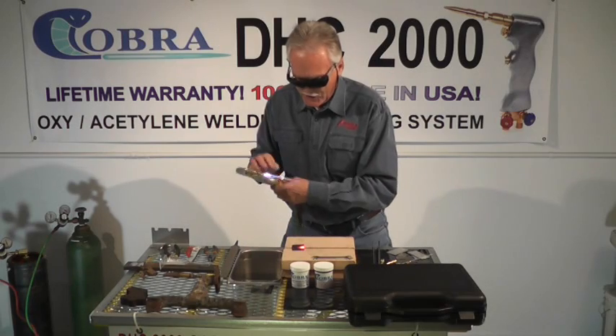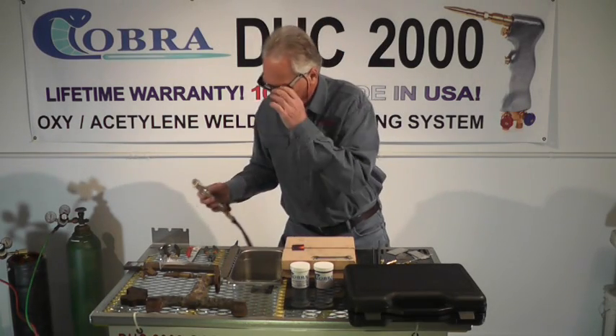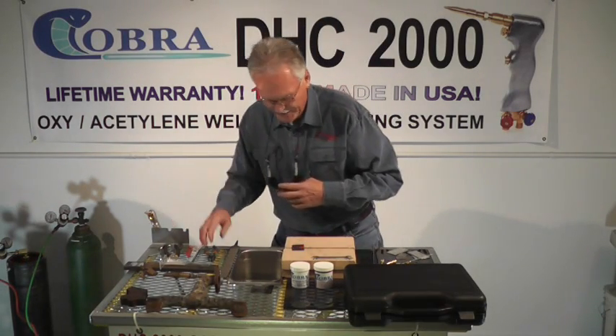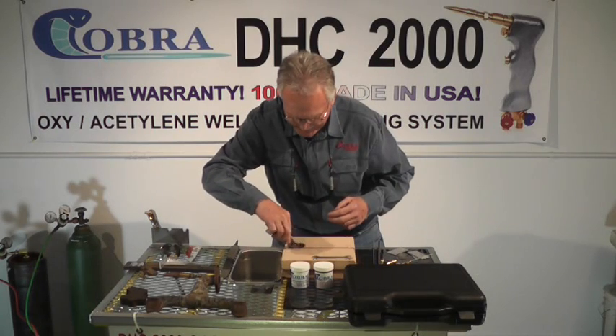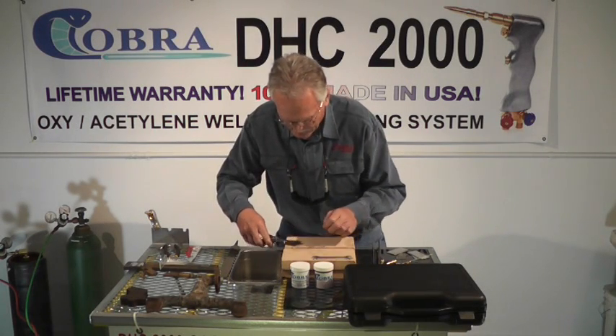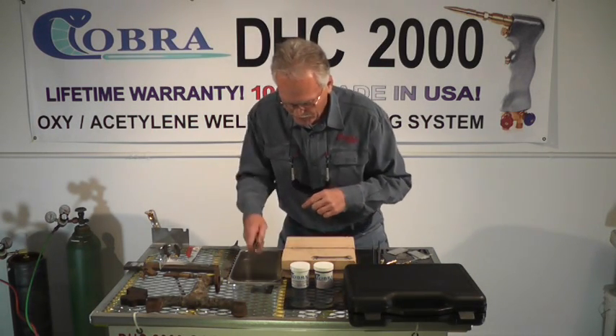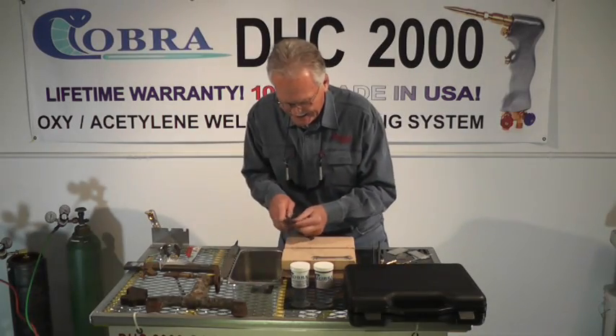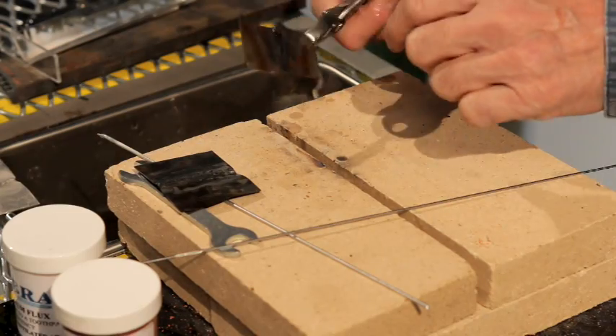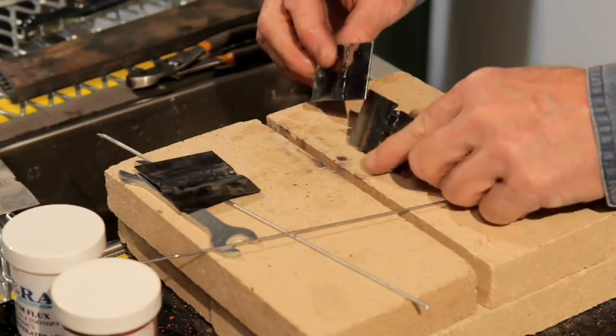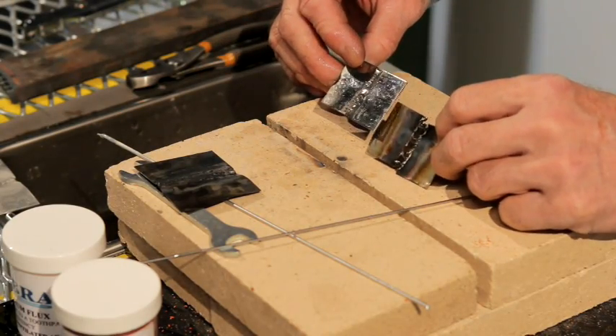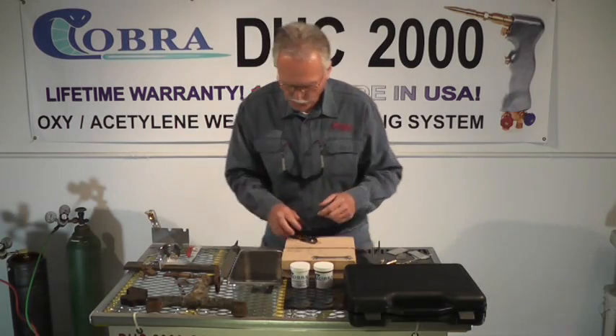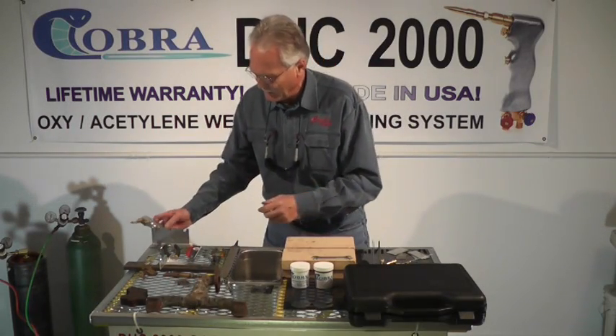Now you're going to get a dark looking weld when you weld with it because of the excess acetylene. You can see your weld, your 100% penetration on it, the stainless. Now see, you get a dark looking weld with it. Jeweler's rouge and a buffing wheel will buff it out just like a mirror, so it cleans up very, very nice.